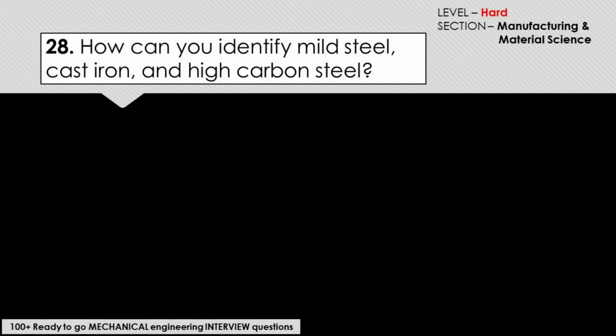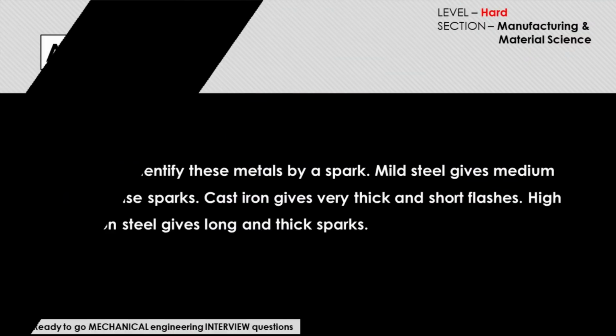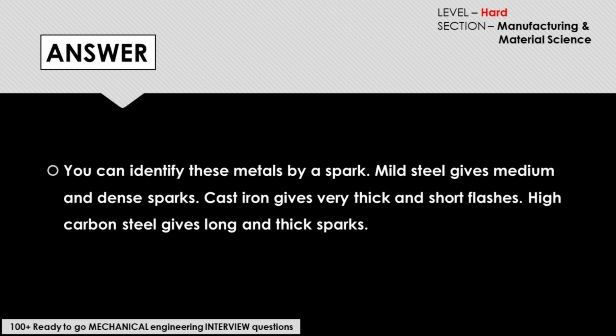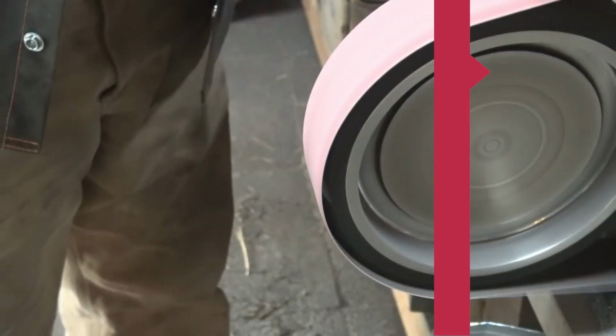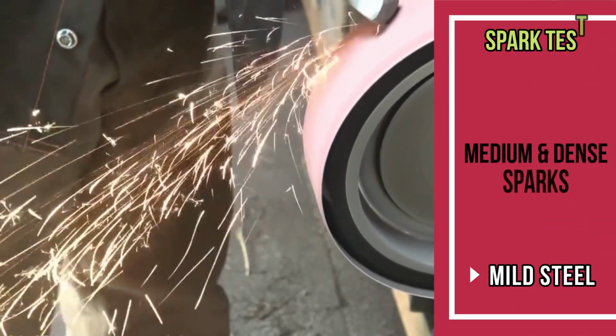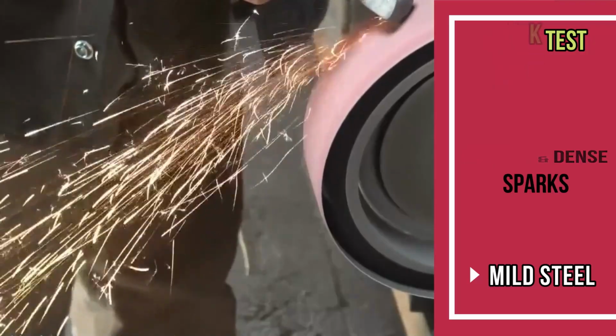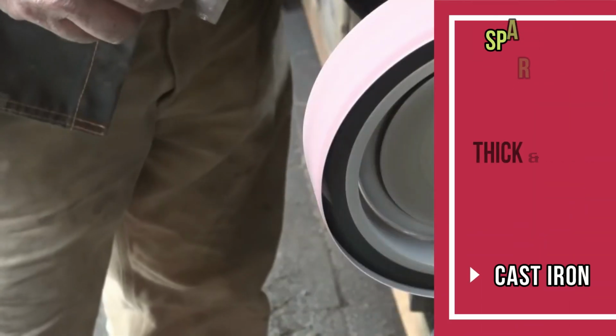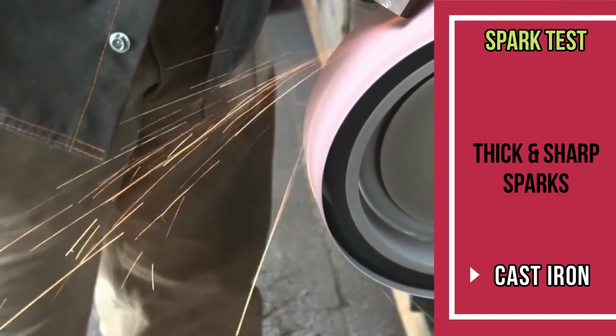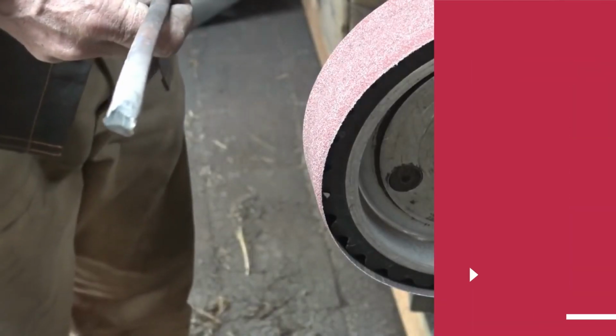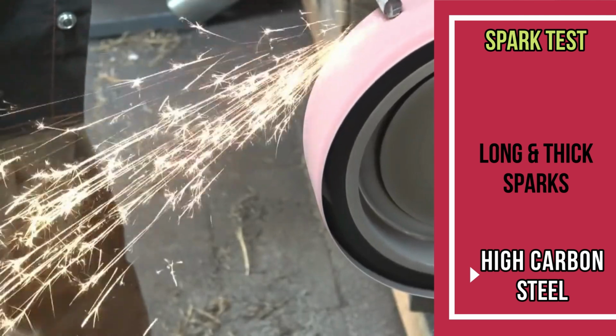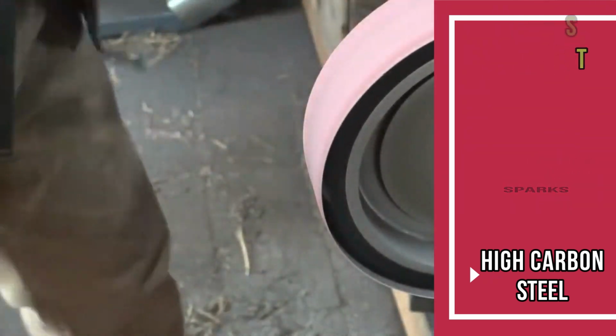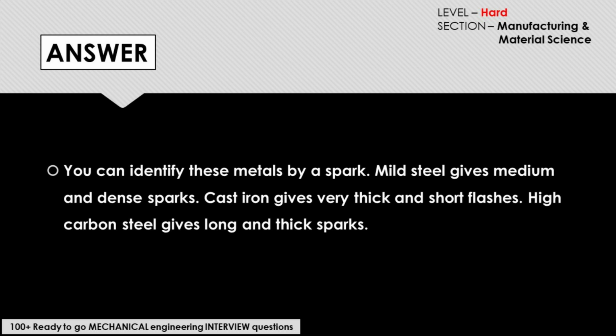How can you identify mild steel, cast iron, and high carbon steel? You can identify these metals by spark testing. Mild steel gives medium and dense sparks. Cast iron gives very thick and short flashes, whereas high carbon steel gives long and thick sparks.